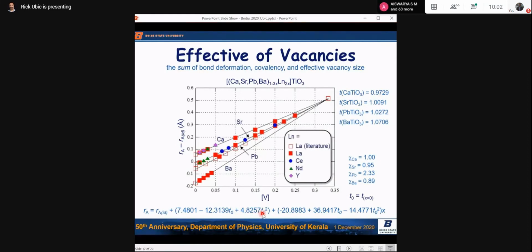T0 is the tolerance factor for the x equals 0 composition, if I remember correctly. And then from the slopes, we get something to do with the vacancy size. So that's where this term comes from. Again, T0 is the tolerance factor when x equals 0, and x is the concentration of vacancies. It's the x from here, right? Which is the concentration of vacancies.